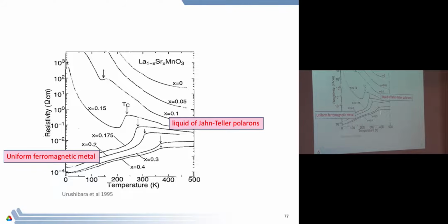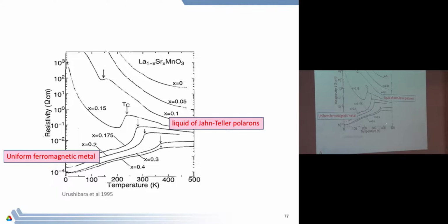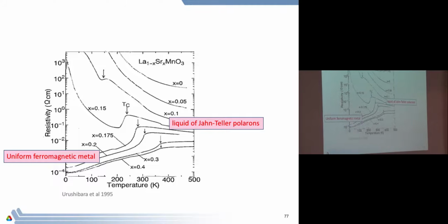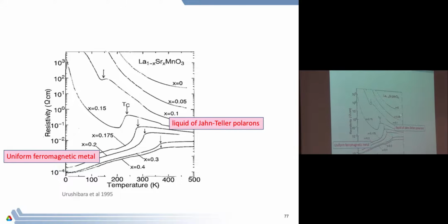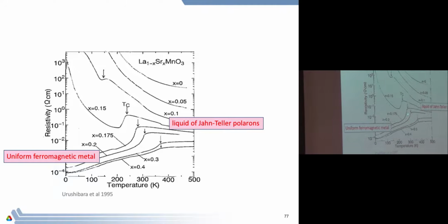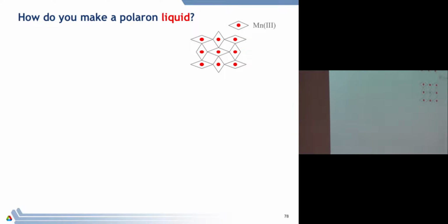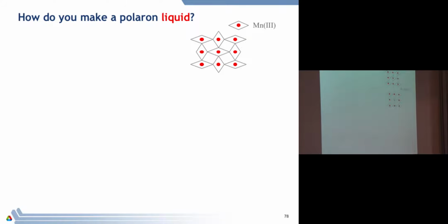That's what happens in these materials, in lanthanum strontium manganese oxide, by varying the doping. As you go from very small x, it's an insulator. As you put more and more carriers in there, eventually this ferromagnetic metal takes over, and you have a metallic phase. And this transition here is an interesting one, because you're going from a metal to something which is really nearly an insulator, because the carriers have been trapped, but they've been trapped into something which isn't ordered. And so then I should ask, how do you do that?